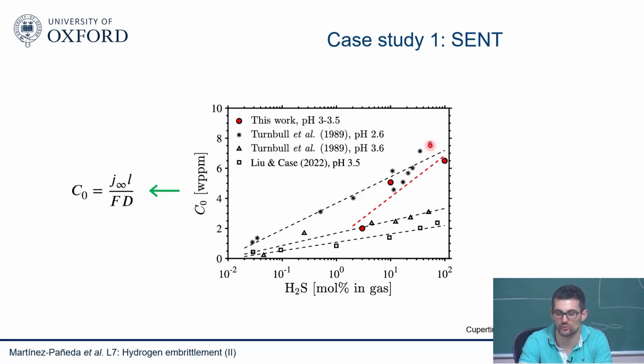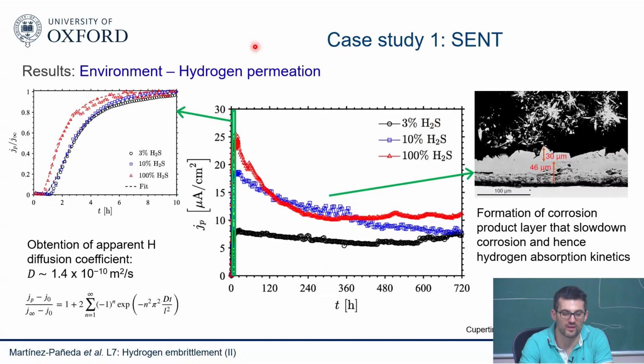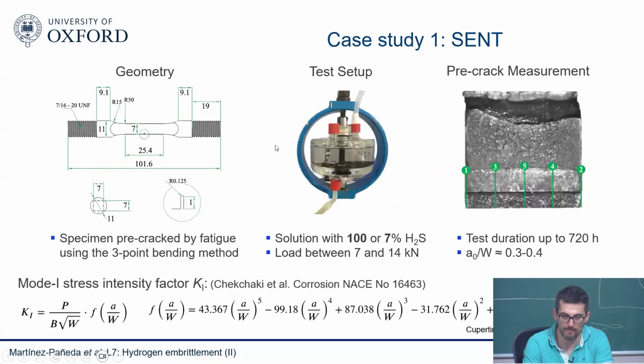So an increase in hydrogen concentration with H2S. Again, when we think about the first stage, before we block things from coming in. So then what we did is we did the fracture experiments, the SENT experiment. So this is a single edge notch tension sample.